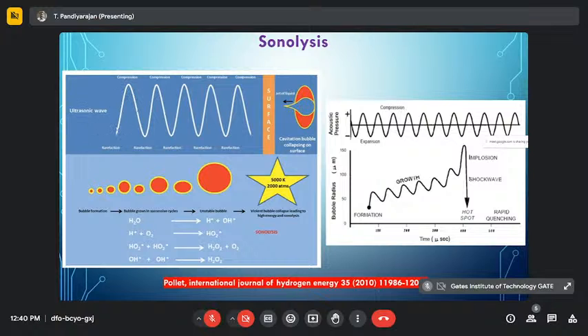Okay, so what is an ultrasonic wave? An ultrasonic wave is something like a compression and expansion, right? So that is the ultrasound wave. If you send this ultrasound wave into liquids, what will happen? This will create a kind of bubble. In the beginning, there will be bubble formation, and over a period of time, around microseconds, the size of your bubble starts to increase. Once it reaches a particular size, around micrometer size, it will start to collapse.